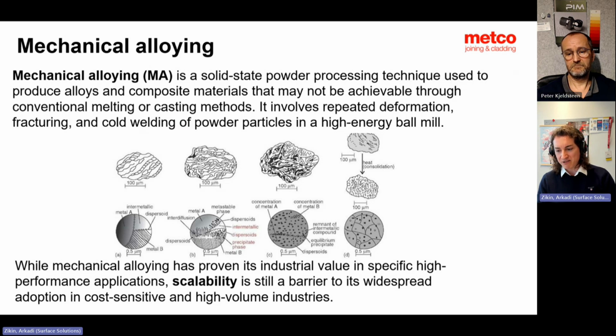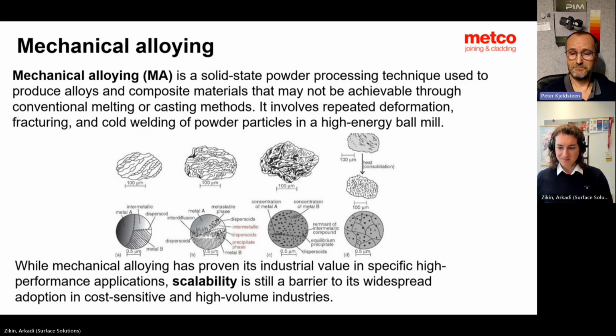So basically you alloy powders not during the sintering stage, you alloy them by cold welding. And that's how you make the transformation. So that's how you also transform titanium dioxide to titanium carbide, with this permanent fracturing causing carbon to react with titanium. And as I said, in my opinion, the biggest problem of this technology is the scalability. Yeah, and it's costly. It is costly.